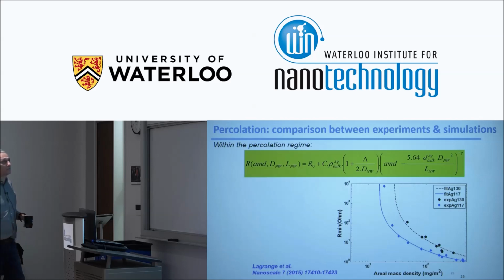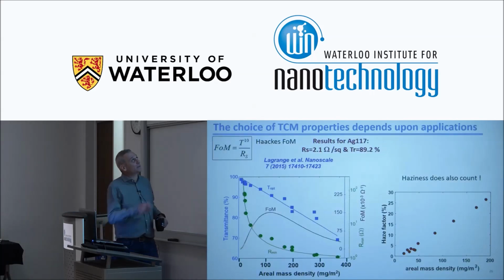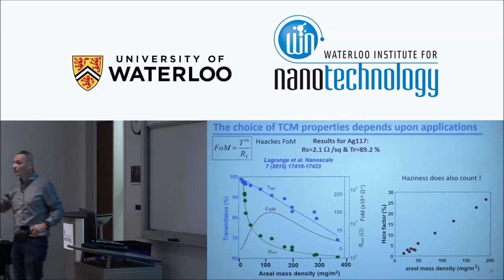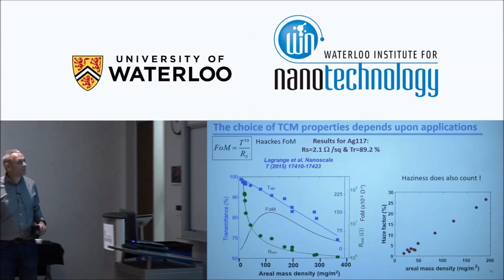And so that means we have a kind of a formula for the figure of merit. You see what we do here? We use again the figure of merit, T to the power 10 divided by the sheet resistance. And we plot experimentally the optical transmittance versus the areal mass density. This is a linear decrease. It's rather easy to understand if you are considering the shadowing effect. The more metal you put, the less transparent will be the transparent electrode.